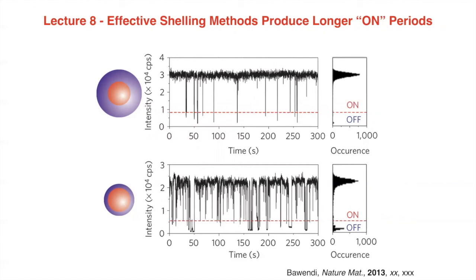And if you take all of the points on this plot spread out in time and you bin them together, you can look at the intensity, the probability of having emission at this intensity versus, say, that one. And you can see really there's only a little bit of the time do you see particles falling into this bin here and luminescing in this sort of gray kind of a way. And then if you make a thinner shell, you'll find that the ratios change, and the distinct type of emissive states evolves.